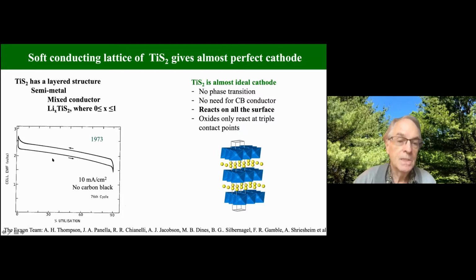So you can see a typical discharge curve here. This is at 10 milliamps per square centimeter discharge and charge. And I went back and looked at the original patent, and the loadings of TiS2 we used back in those days varied between 20 milligrams per square centimeter up to over 100. So we're using very high loadings.